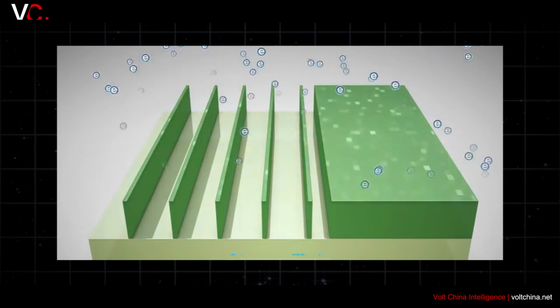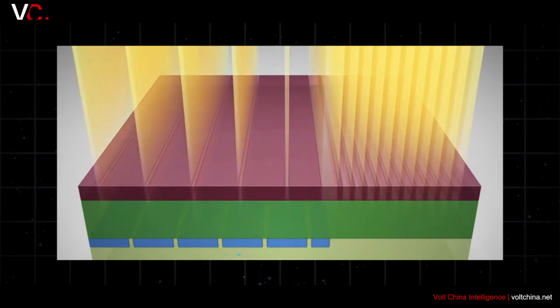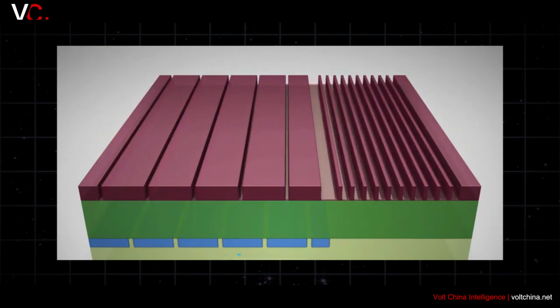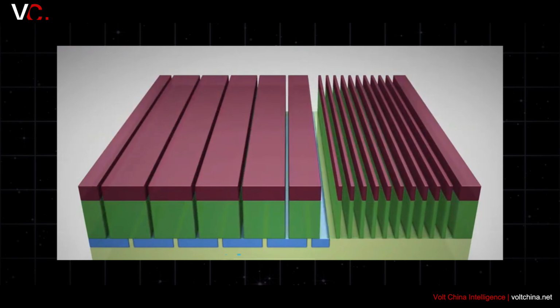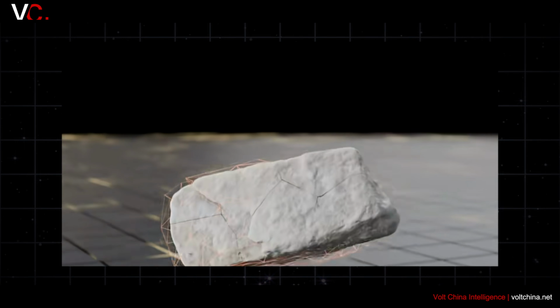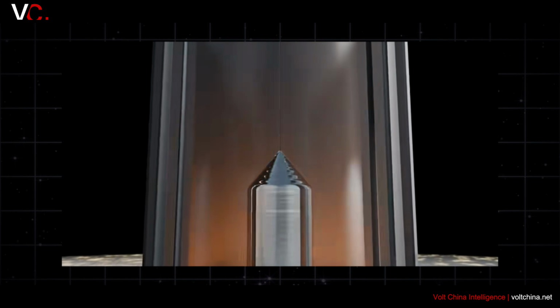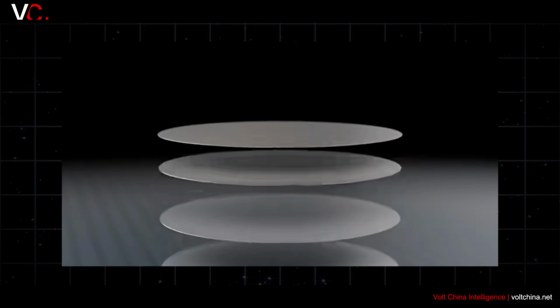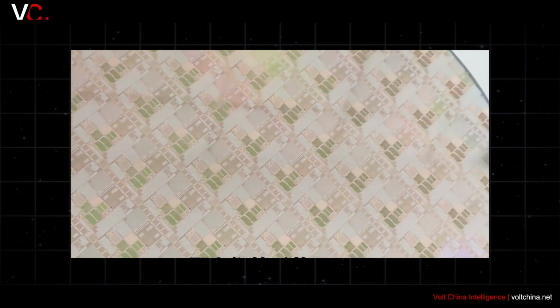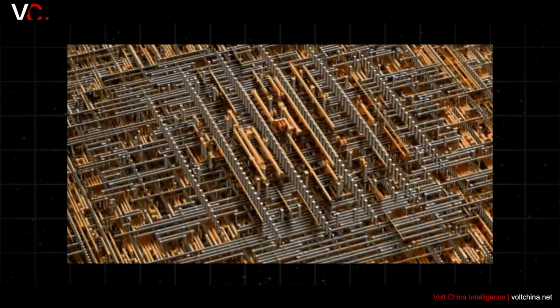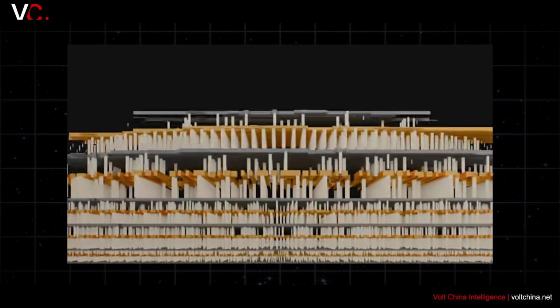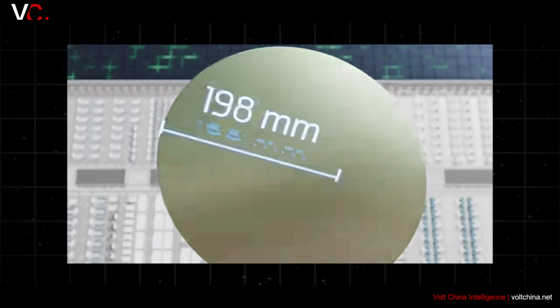Here is how Chinese engineers solved this. Companies like SICC and TanKeBlue rebuilt the growth methodology from the ground up. SICC secured 194 invention patents, focusing on the exact root cause of wafer failure, residual internal stress. By utilizing advanced numerical simulations combined with enhanced forced convection and hemispherical radiation shields, they stabilized the temperature uniformity at the growth interface. This localized temperature control directly translates to flat, low-damage single crystals. The result? SICC's substrate cost is now 33 to 40% lower than Wolfspeed's. TanKeBlue followed suit, slashing their single wafer production cost by 37% year over year.